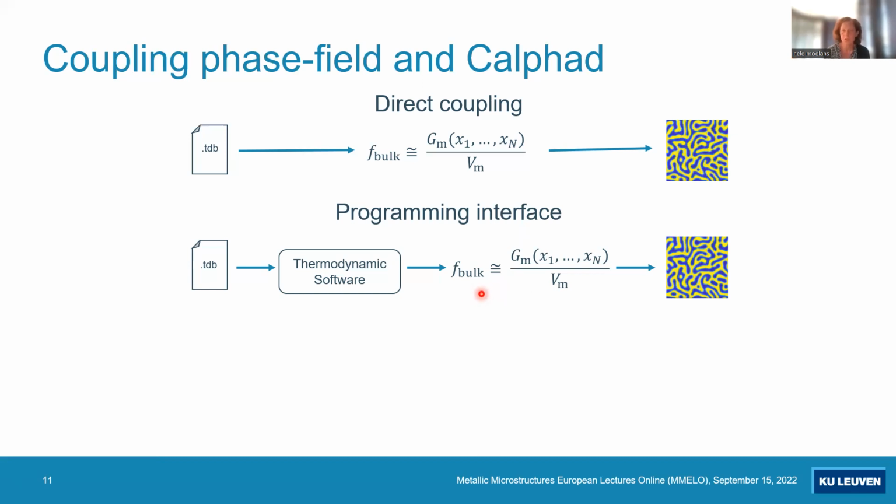If you work with dilute solutions and binary solutions and even ternary solutions, people have developed methods to minimize the number of times that you have to make a computation. But these methods are, of course, based on interpolations and extrapolations, and mostly linear interpolation. And if you want to do that for a quaternary system, actually it requires a lot of computations, and also the interactions between the different elements are stronger, and so a linear interpolation is not always that accurate.